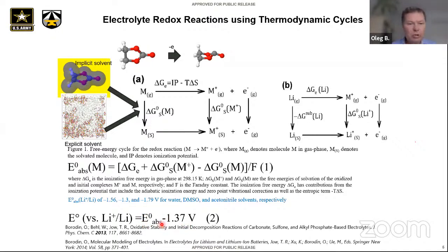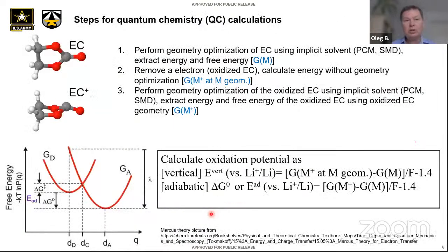And there is an important caveat, which I think is often overlooked: the absolute potential is different in different solvents. That tells you that this correction factor is probably accurate within 0.1 to 0.2 eV, and you shouldn't read much more into it if you're looking at the various solvent variations. So how do we do that in practice?